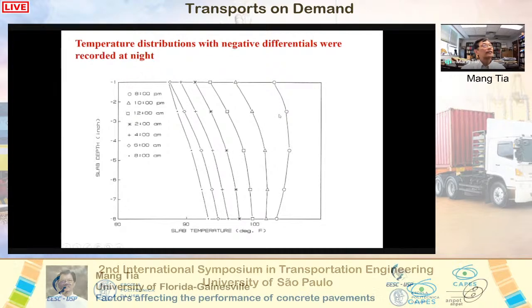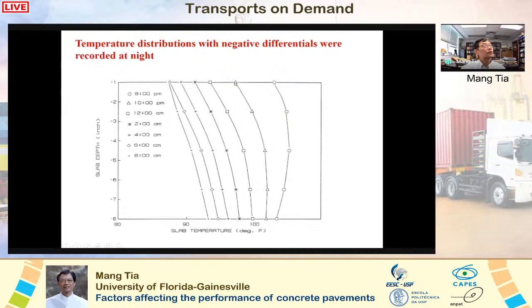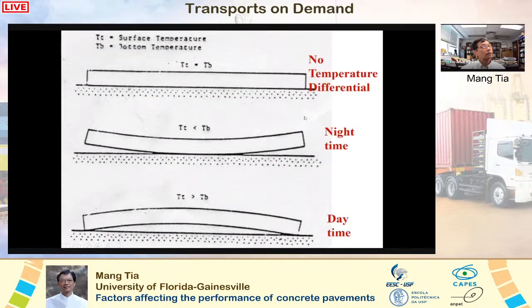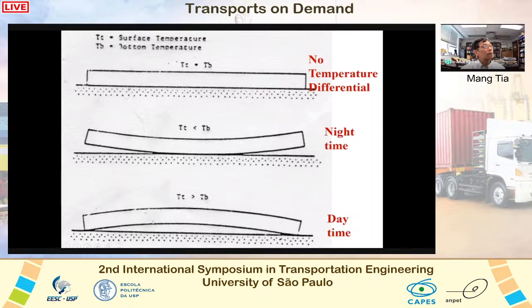At night, it's the other way around. At night, the temperature is lower at the top than at the bottom. And this shows temperature distributions at different times at night. Well, at nighttime, when the temperature is lower at the top, the slab may curl up at the edge, as shown in the middle figure here. In the daytime, when the temperature is higher at the top of the slab than at the bottom, the slab may curl up this way, as shown in the bottom figure.